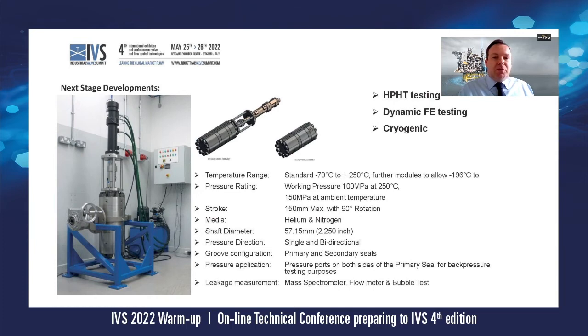And a custom environmental chamber has been added to allow us to test at temperature ranges from currently approximately -70 to +250 degrees C. And this now brings our test criteria much more in line with actual conditions in valves across the upstream and production sector. So, shorter test than an actual valve, this is probably about as close as we can get. And we will be able to assess the impact of stroke speed, clearance gaps, and other valve type variables on the leakage rate and lifetime performance of the stem arrangements. And it will greatly enhance our ability to advise clients on optimum conditions for achieving a successful test within their own equipment.